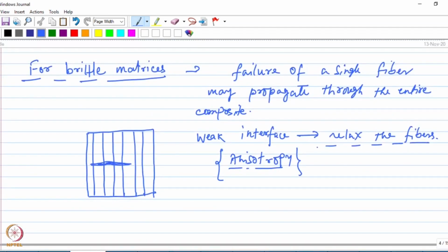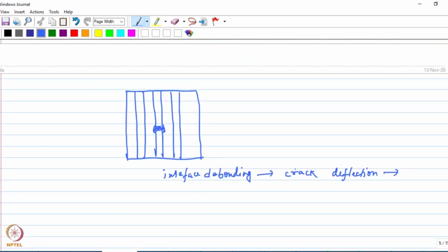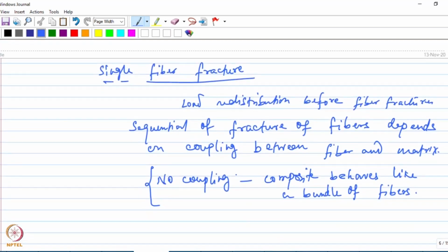On the other hand, when it is a brittle matrix, the crack can propagate from one fiber to the adjacent fiber, and the catastrophic failure can only be prevented if there is a weak interface which leads to some kind of deflection of the crack due to the debonding at the interface. Okay, and then we talked about the fracture of single fibers as to how the fibers fail one by one when the composite is loaded, and this sequential fracture of fibers depends on the coupling between the fiber and the matrix. If there is no coupling, the entire composite will behave like a bundle of fibers, and on the other hand, when there is a strong coupling, the fracture behavior would depend on the interface bonding.